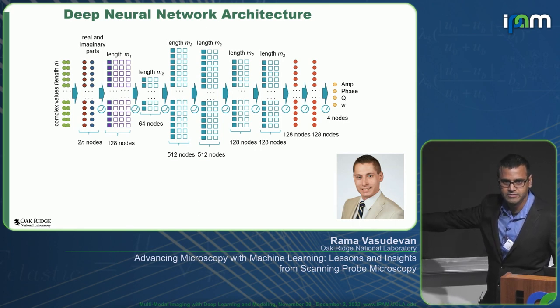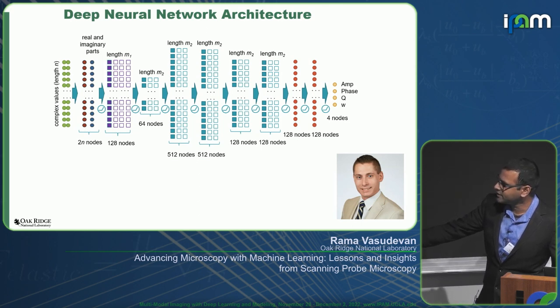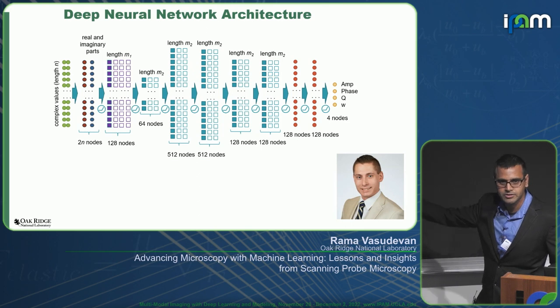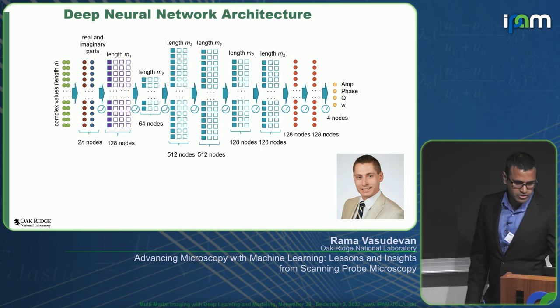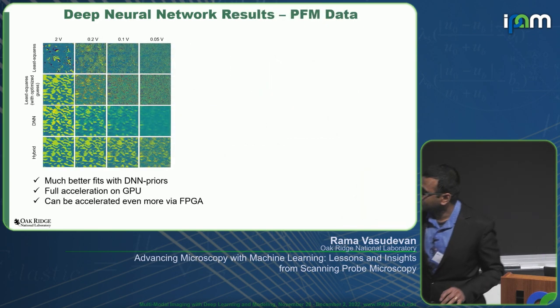We can train on millions of different examples. And so it actually works out to be a really good estimate for priors, which we can then use for our functional fits. So let me just show you how that actually looks in a real case. Here on the top left side, you see a standard inversion from least squares of a particular image captured at 2 volts, right? So this is a typical voltage that we would use to capture these kinds of images on ferroelectric materials.